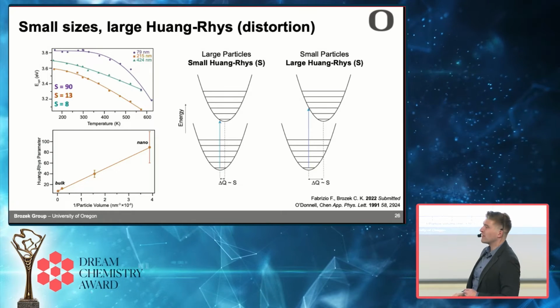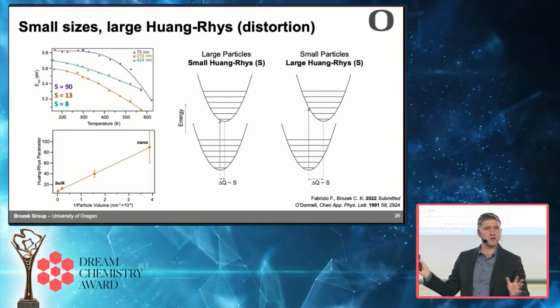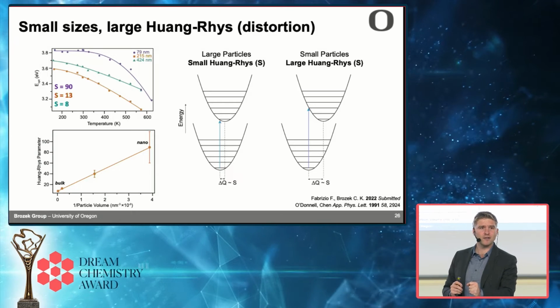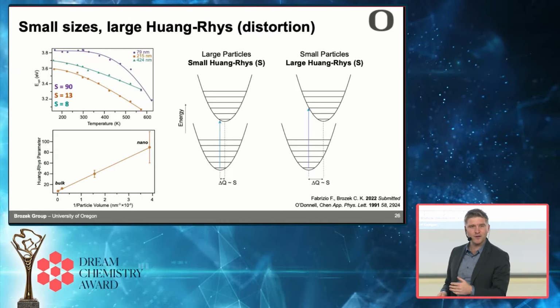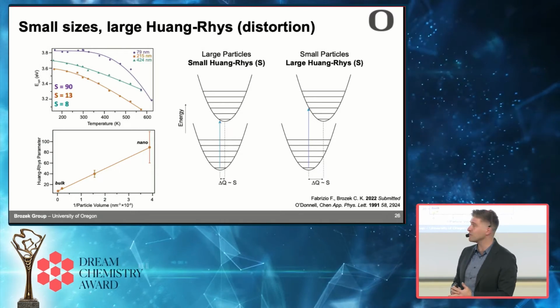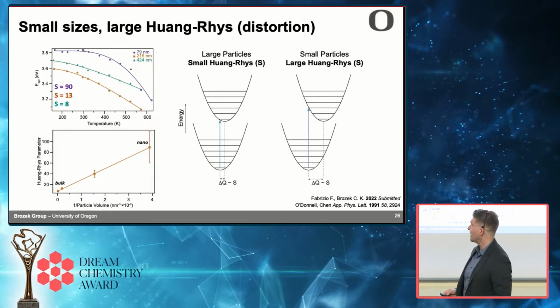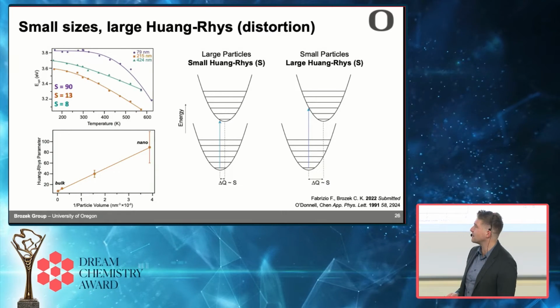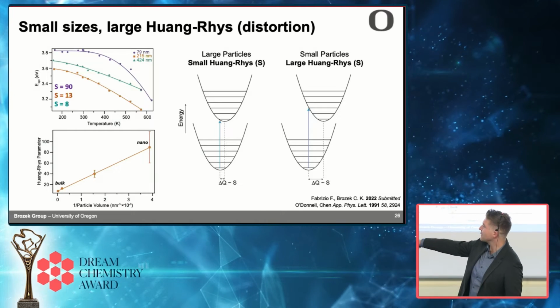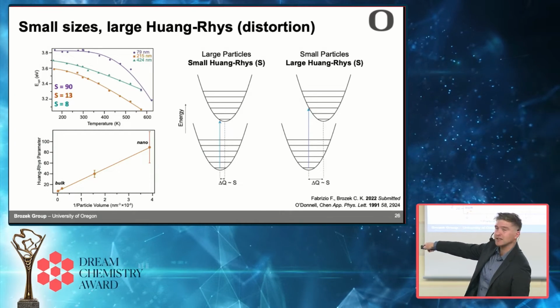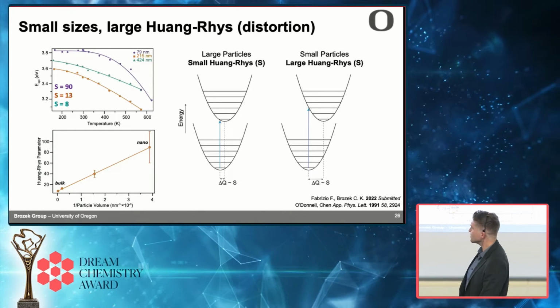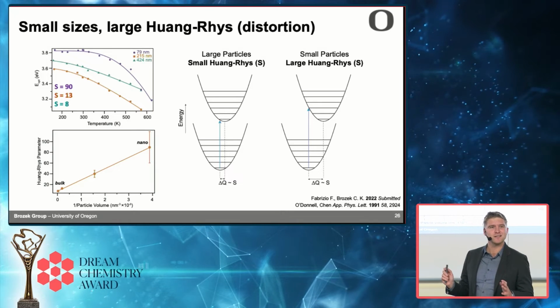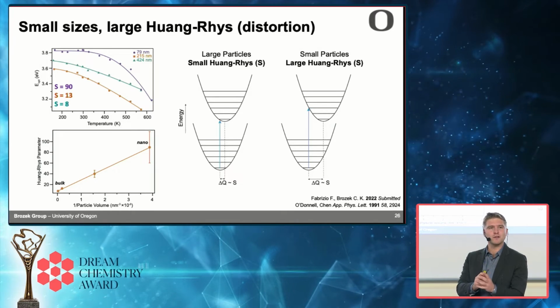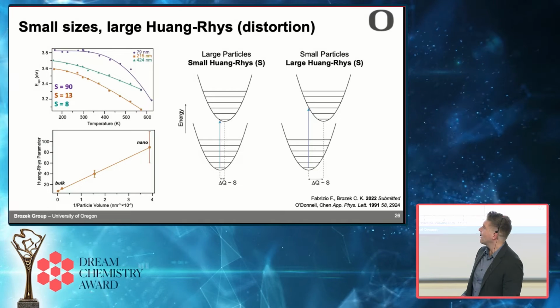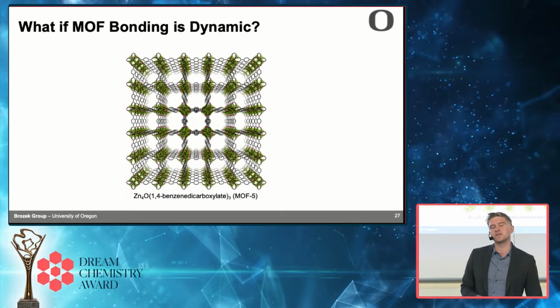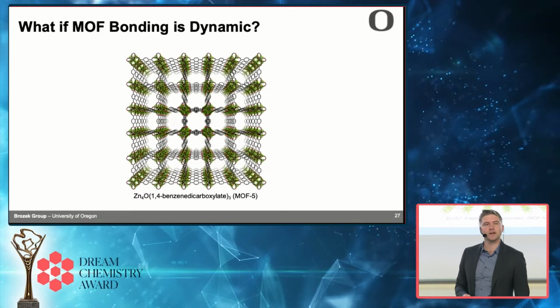A typical Huang-Rhys parameter for a molecule, so you can measure this for, if you have the optical gap for any small molecule, or even a typical semiconductor, a Huang-Rhys parameter is around 1 to 10, and we're seeing values that are almost 10 times that by making the particles smaller. We see that it's really size dependent. In fact, it tracks really nicely with particle volume. So this kind of leaves this impression for us that somehow you make MOF particles smaller and they get more flexible.